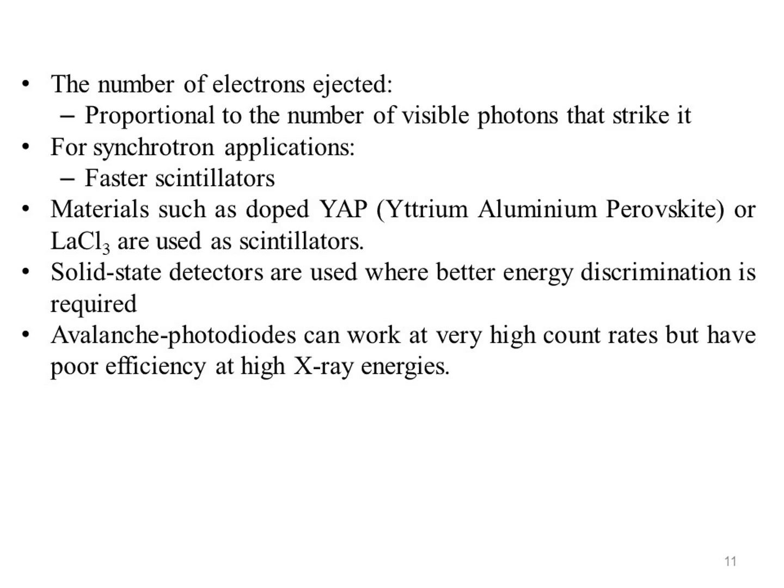For synchrotron applications, faster scintillators are often needed, and materials such as doped YAP, yttrium aluminum perovskite, or LaCl3 are used as scintillators. However, their light output per incident photon is less.